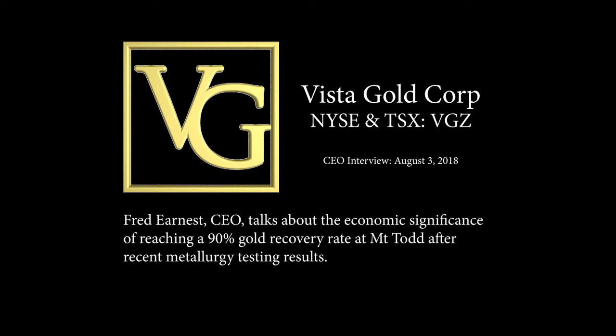We're now going to be undertaking a series of grinding and leaching tests. We'll be doing more work with Core Labs to test using the IsaMill technology. We'll be running those tests on ore samples that have higher grade. Some of them will be mixed ore samples so that we can estimate the complete range of ore types that we'll have, as well as the grade of material that we'll process so that we can generate a grade recovery curve, validate that we are in fact at a grind size where we're achieving a constant tail. And when we get all this finished, we're going to take a step back and look at whether these results merit restating the economics of the PFS study that was updated in January of this year.